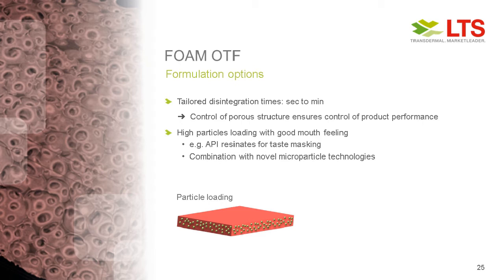Since there's a different thickness of this foam, it's not just a thin film of only 100 microns, we can nicely load these OTF foams with particles, and due to the thicker structure, it does not feel like having sandpaper in the mouth, like old OTC products, especially in the US, had, a mouthfeel which was not really favorable to patients. By having this foam structure, particles like API resonates, for example, which have been used for taste masking, are very often incorporated much more into the foam, and therefore the patients do not really taste them and have them as a negative mouthfeel experience. Also, other microparticulate technologies can be used in combination, and this is really open for that.